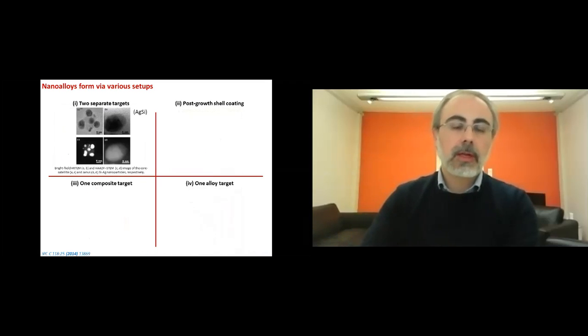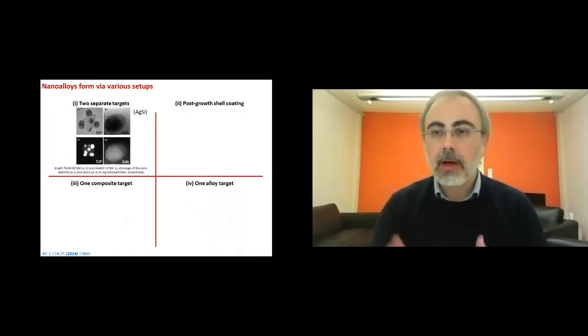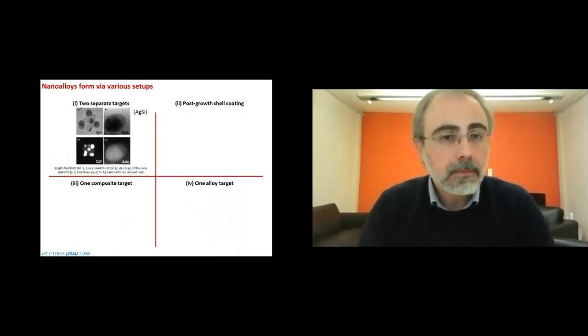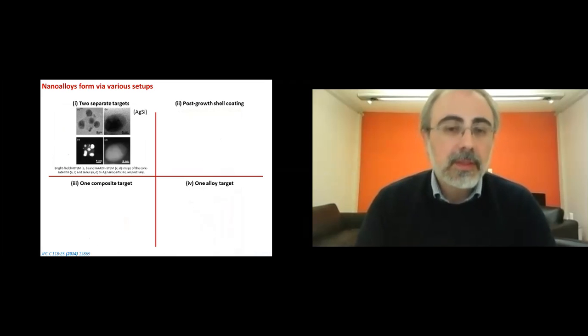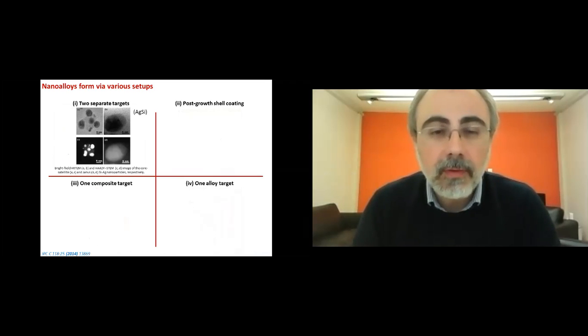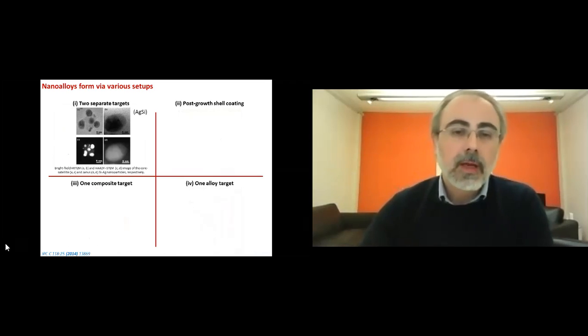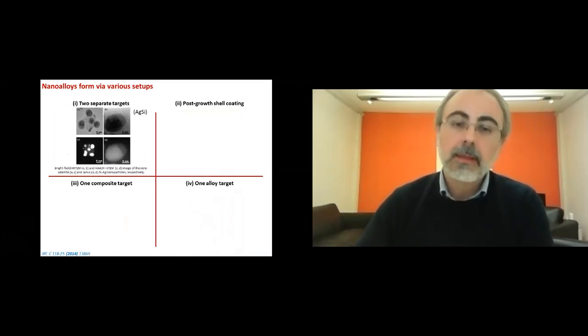And here, let me show you a little bit of our experimental results to see how they compare with the simulation. So in the first case of silicon silver clusters, you can see that we have these Janus particles. For example, in these HAADF STEM images, the different intensity, different brightness indicates different elements. So silver is the bright spots and silicon is the darker, the gray spot.